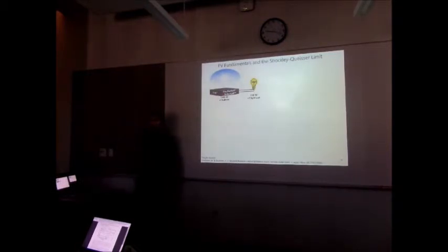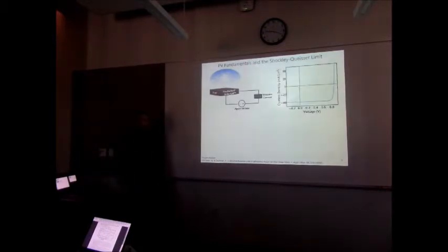So I want to take a quick step to the side here and talk about PV to help frame the rest of my talk and what I'm trying to do. So if I imagine the perfect solar cell, as first described by Shockley and Queisser back in 1958, under one sun illumination, you would get 1,000 watts of light in roughly, but you'd only get 310 watts out. This is sort of a fundamental limit for a solar cell. So it's only about 31% efficient for the ideal band gap.